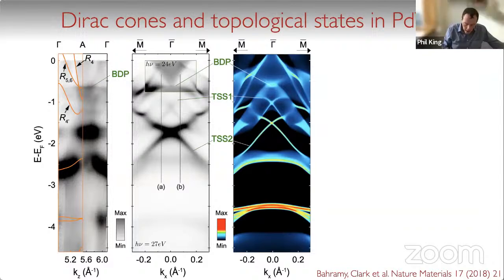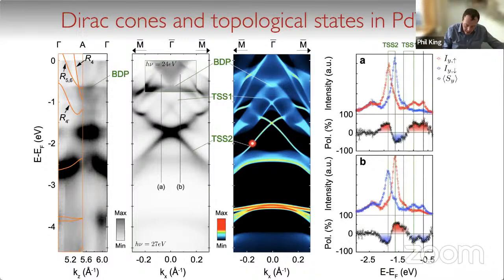I think you're thinking about Rashba type states, but here this is a spin polarized Dirac state, a topological surface state where we just get a single Dirac cone. You can see from this spin resolved measurement that you have opposite spin textures on either side of plus and minus k, and so this is a single Dirac cone surface state with a chiral spin texture, much like you would get on the surface of bismuth selenide or something like that.